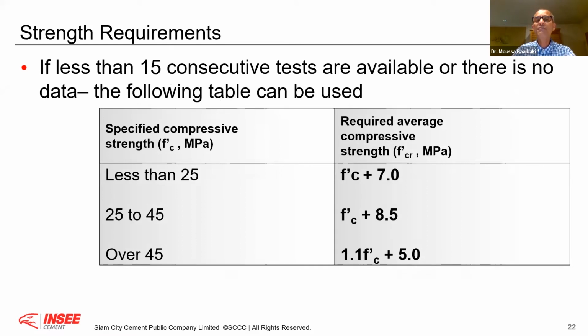Now, if it is less than 15 consecutive tests, this is really when you don't have data, like in the bad market. In the bad market, if I design a concrete less than 25, I have to add 7 megapascal. If it is 25, I should design 33.5 megapascal. This is why, if I look at the cement utility factor, which is how many kilograms of cement I need to get 1 megapascal, normally in ready mix operation we need less than 10 kilograms. We are around 7, 8 kilograms per megapascal.